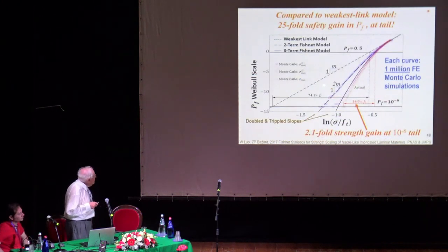The result is this. If we plot probability on Weibull scale, Weibull distribution, the weakest link model is a straight line. This is the Weibull modulus. If we do exactly the fishnet, I call it fishnet statistics, failure with up to two links. This is failure where one link decides. If you need two links to cause failure, you get this curve. If you need three links to cause failure, you get this curve. These are analytical curves, exactly agree.